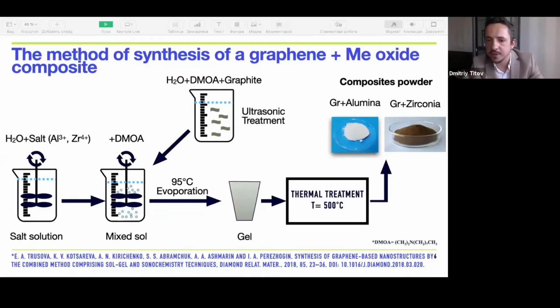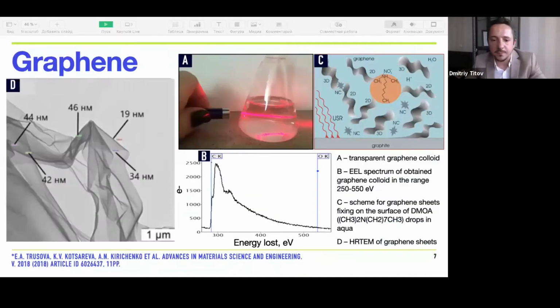Here you can see two powders. This is the real picture of the graphene alumina and graphene zirconia nanopowders. The process of obtaining graphene suspension involves 3 steps: exfoliation, dispersion, and stabilization of the resulting suspension. The transparent graphene colloid was obtained in which presence of suspended graphene sheets was confirmed using the Tyndall effect. And the EELS analysis shows that there is no graphene oxide in the obtained graphene. The peak at 500 electron volts corresponding to the oxygen does not appear in the spectrum.